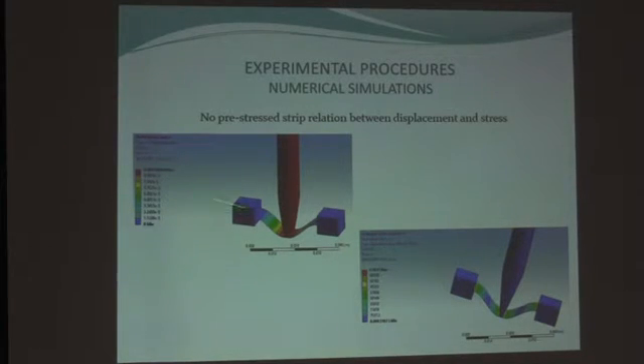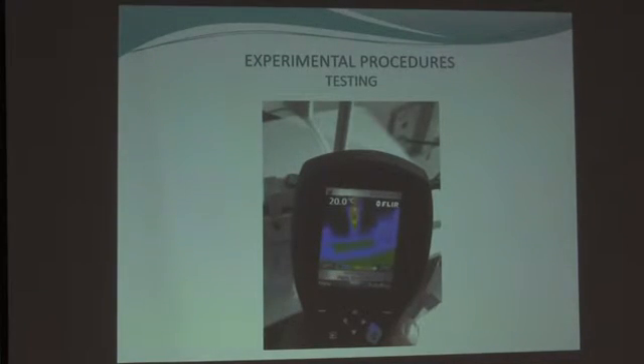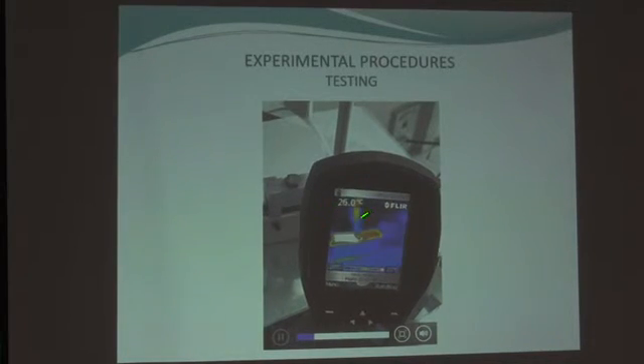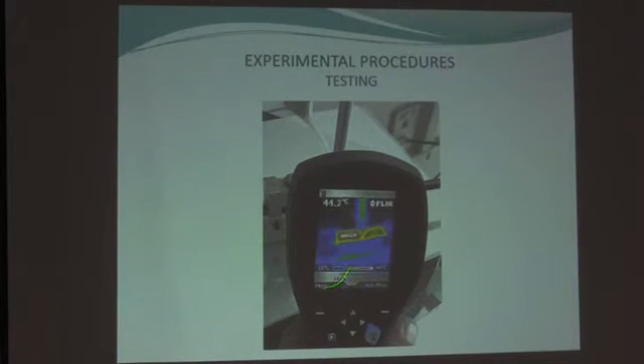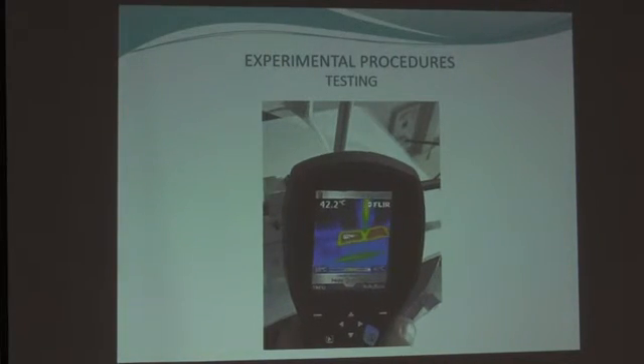Here we have the simulation concerning the displacement. In this case, it's 100 micrometers of displacement inducing about 78 kilopascal. All the tests were carried out in the following condition. First of all, tension for the strip, inducing about 0.46 megapascal, and then applying the horn in the center of the strip and relaxing the value to 0.47 megapascal. Here we have the rate condition of testing. As you see, temperature is increasing, and then we see the condition of real testing loading.